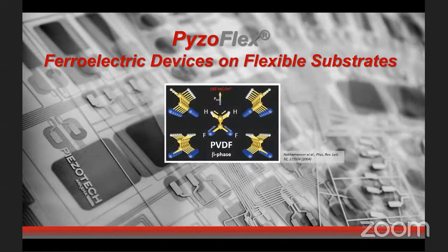The base material of PyzoFlex is PVDF, a fluoropolymer that exhibits a spontaneous polarization of 185 millicoulomb per square meter in its unit cell according to ab initio calculations. The polarization arises from the net dipole moments between the hydrogen and fluorine atoms that are facing each other in the all-trans conformation, and this conformation forms the ferroelectric beta phase.